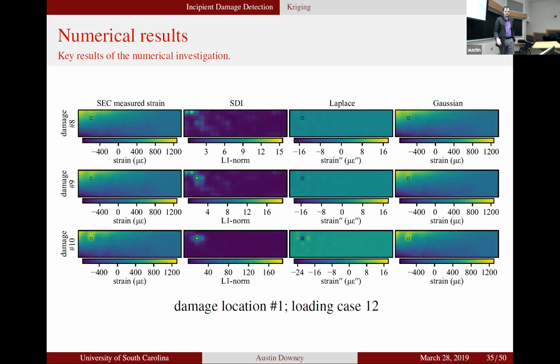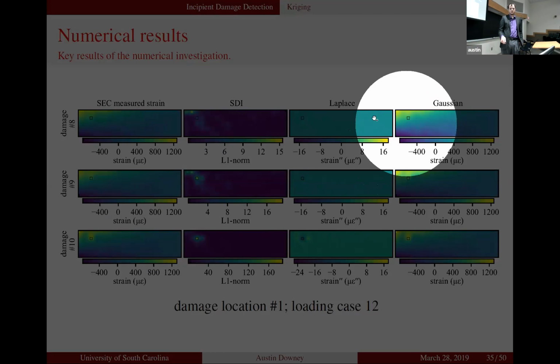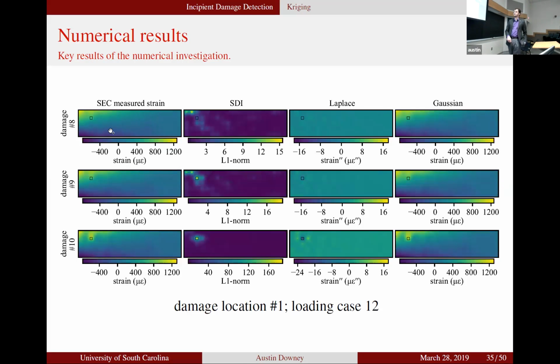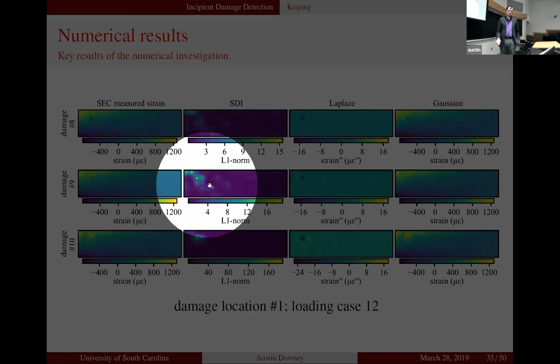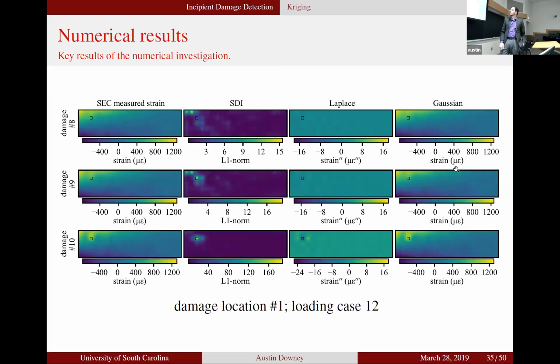And what you'll see is that the SDI does quite well at detecting damage. So on low levels of damage, it'll detect dissimilarities up here around the corner. Obviously, nothing is detected in Laplace and Gaussian. And on the actual strain map, you can't see the damage at all. Once you get to the next level, this SDI algorithm correctly localizes the damage, but you can't see the damage here in the strain map. And then Laplace and the Gaussian don't detect it at all.